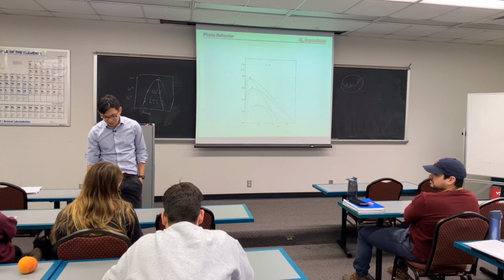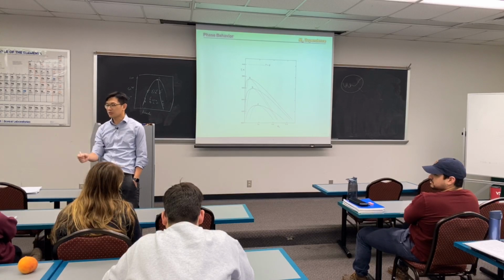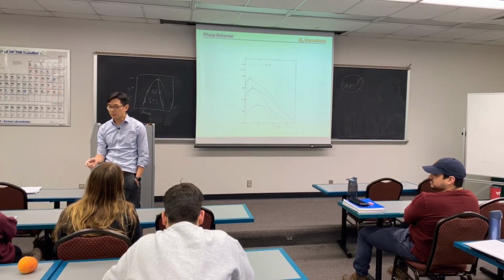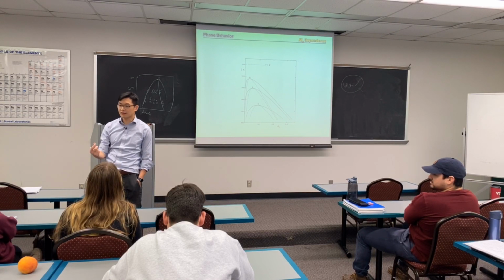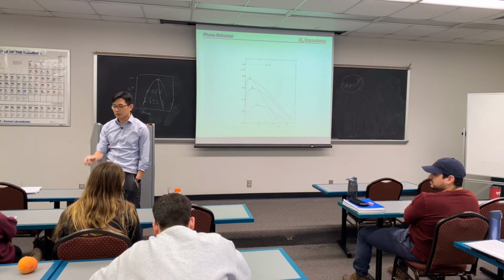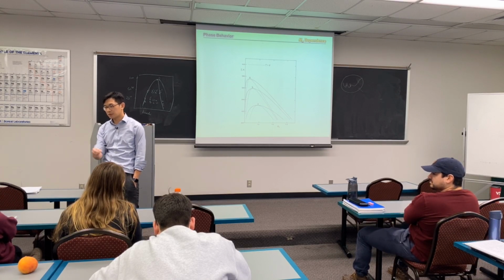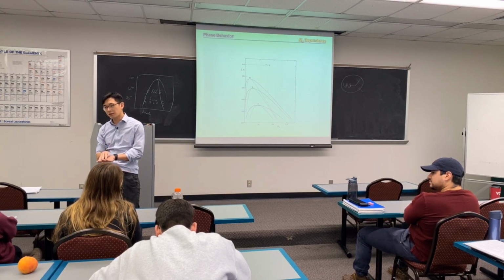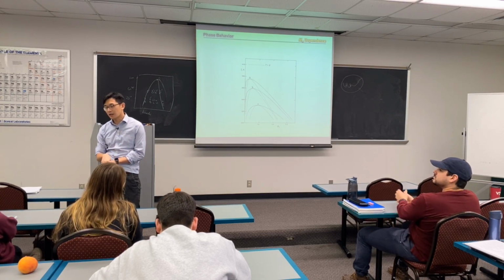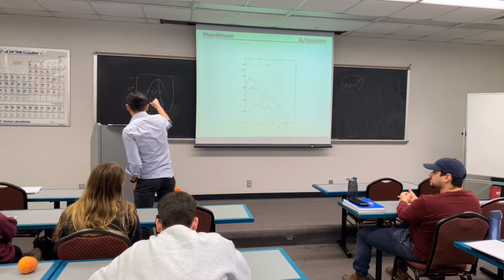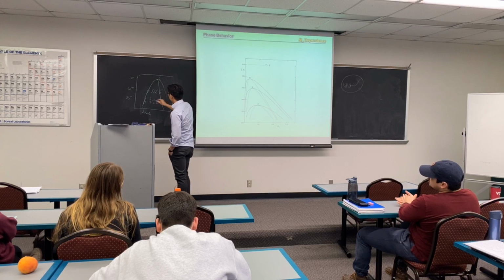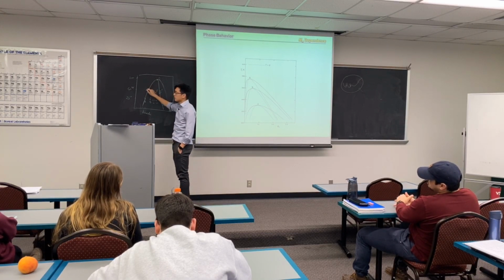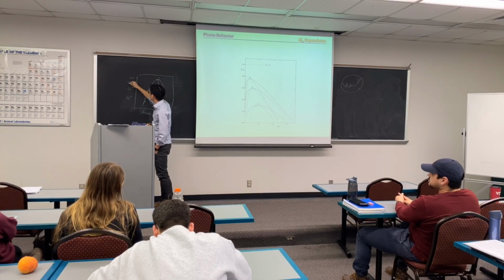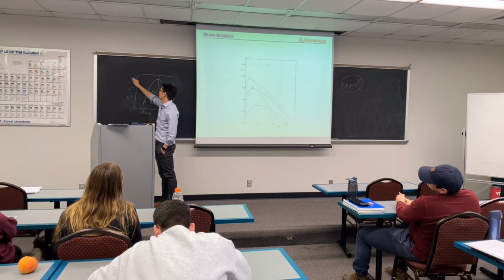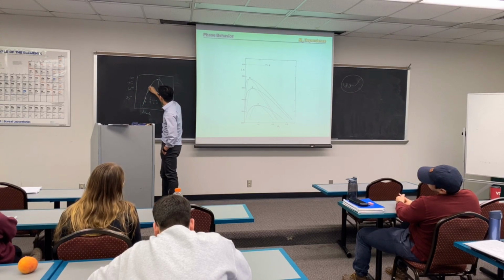So I certainly see what your point is, but a lot of the time phase separation is predominantly studied by two techniques: microscopy and scattering. With microscopy, you can directly see which component is which, and when the phase separates, as I mentioned, it would create cloudiness in the solution, and cloud point determination is one way. And in the phase diagram, you don't necessarily need to get every data point. What people typically do is exactly what I show here. They would get 25 degrees, 75, 100. Then they're just going to plot out the boundary.